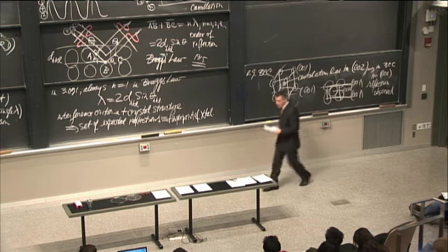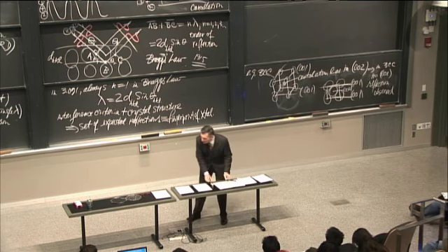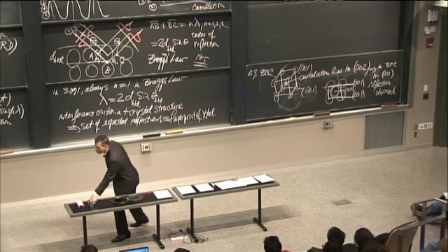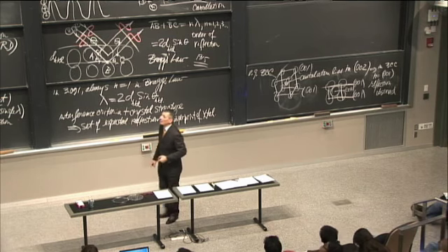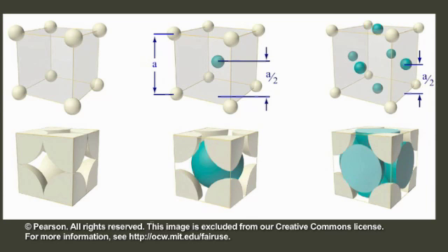So you don't have to worry about all this. This has all been tabulated for you. Somebody's gone through and done all of this. Oh, this is just making the point. See, there's a simple cubic. All the planes are reflecting. There's body-centered cubic. That's A over 2. There's face-centered cubic A over 2. 002 is going to cancel 001. You're not going to see anything there.